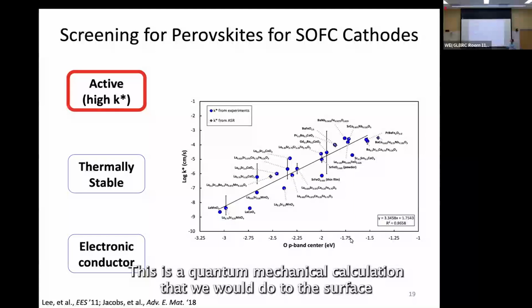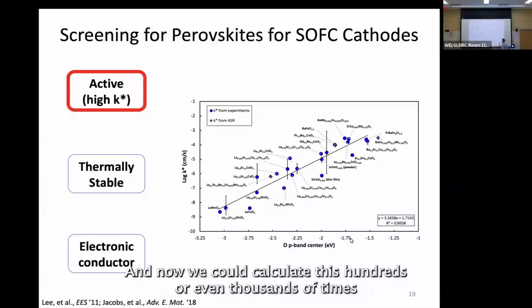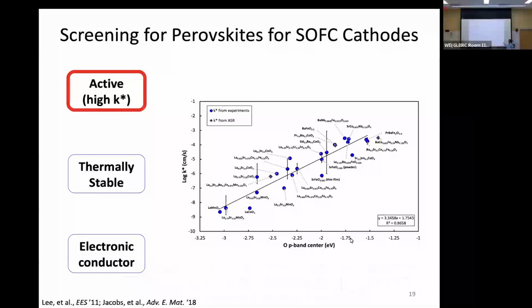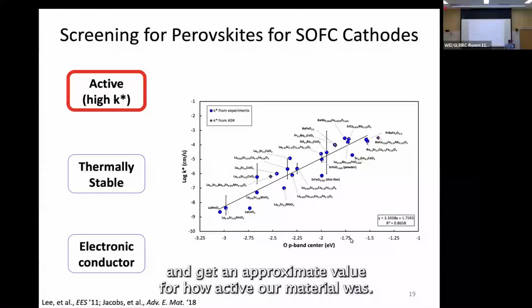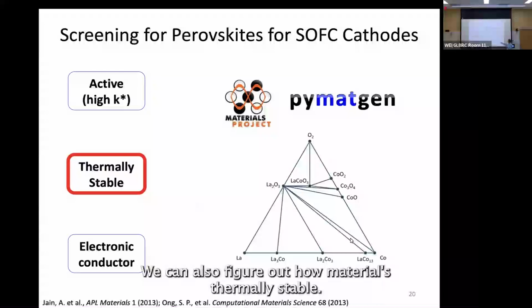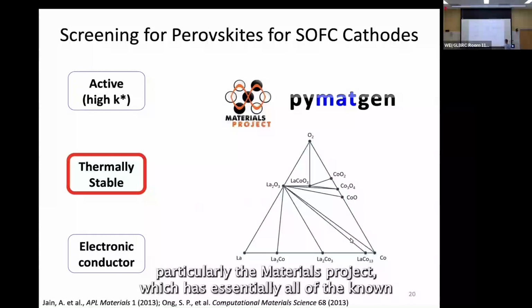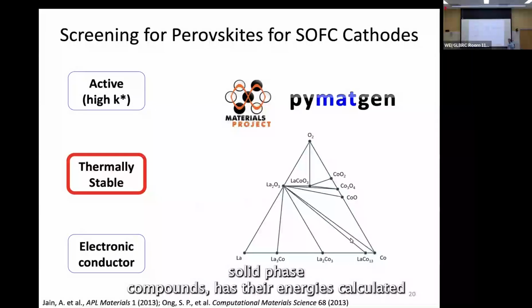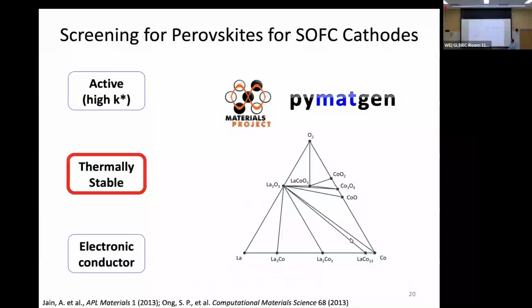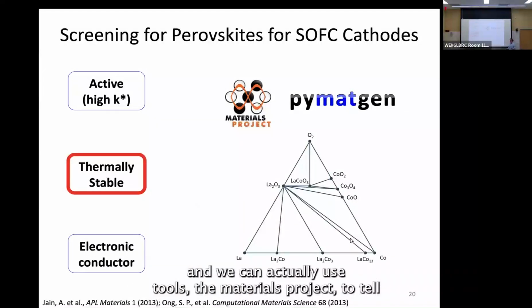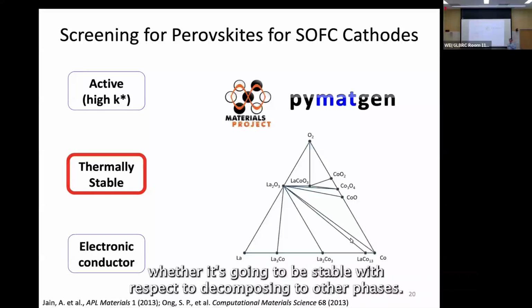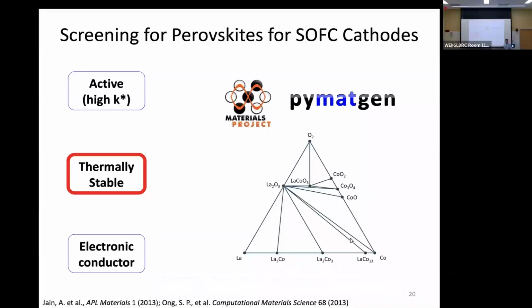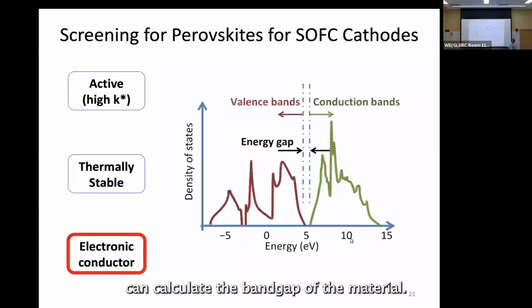Okay, so this gave us access, through a reasonably easy calculation, to the surface exchange coefficient. This is a quantum mechanical calculation that we would do. So now we could calculate this hundreds or even thousands of times and get an approximate value for how active our material was. We can also figure out if our material is thermally stable. And here we use these online databases I talked about, particularly the Materials Project, which has essentially all of the known solid phase compounds, has their energies calculated. So we can take a new compound, a perovskite, and we can actually use tools in the Materials Project to tell whether it's going to be stable with respect to decomposing to other phases. So it's a very powerful way to get at least an approximate guide about whether your material's likely to be stable.